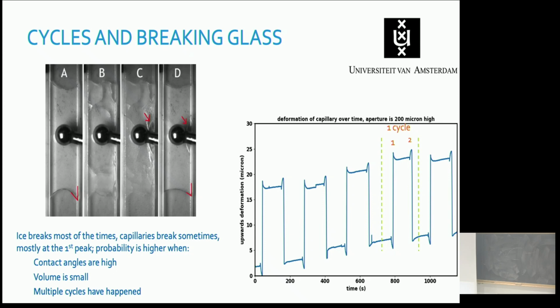And so the further observations, we varied a lot of parameters. We basically only see damage if the contact angle of the water with the wall is high. We have to have very small volumes. If we have very small volumes, we get more damage. And multiple cycles indeed give more damage, as is observed on real materials in the field. And so quantitatively, this is what I just said.